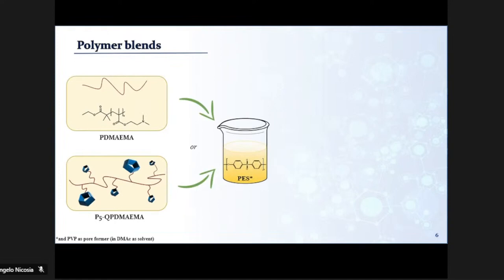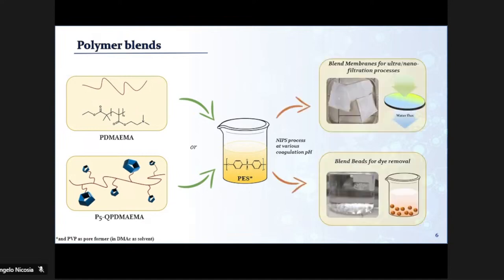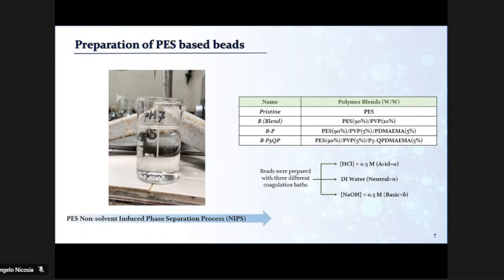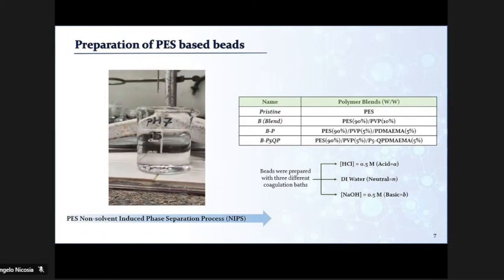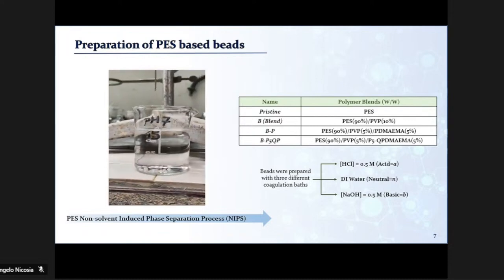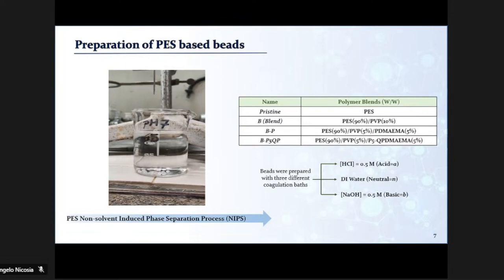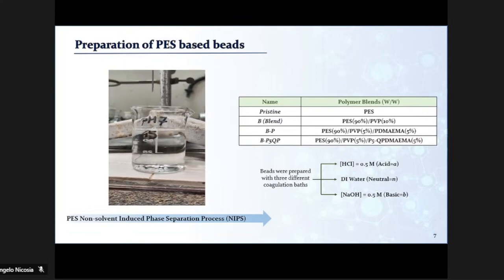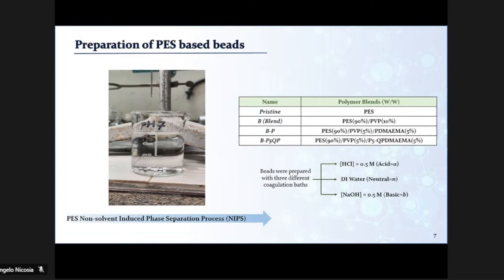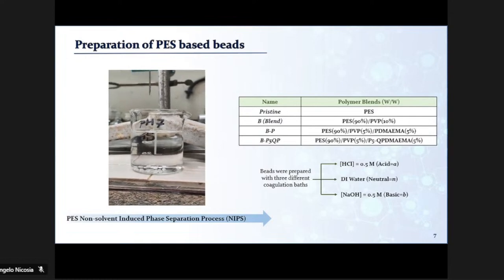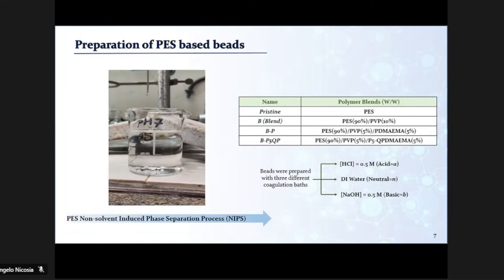Finally, we decided to blend polyether sulfone and polyvinyl pyrrolidone, employed as pore former, with these two smart polymers to obtain, by the non-solvent-induced phase separation process, membranes and beads. This is a very short video in which I show the preparation method of the non-solvent phase separation process. And we prepared different polymeric blends, employing 3 different coagulation baths, properly to study the pH responsive effect of the polymer.